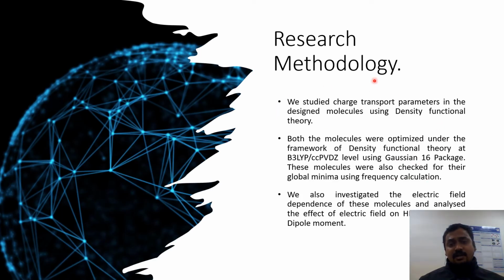So my methodology was to work with density functional theory. Theoretically, we modeled these molecules and looked at their charge transport properties. We used a hybrid functional and a polarized valence double zeta basis set for these calculations. And we also looked at the electric field dependence of these molecules and analyzed its effect on the HOMO-LUMO gap energy and the dipole.